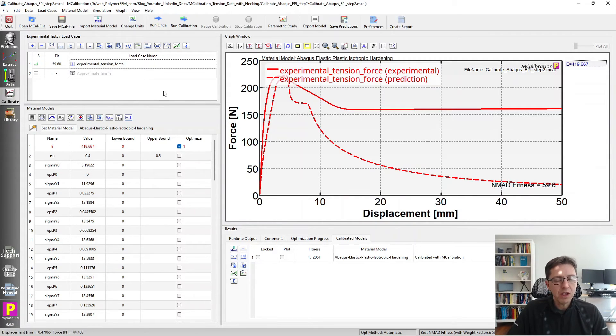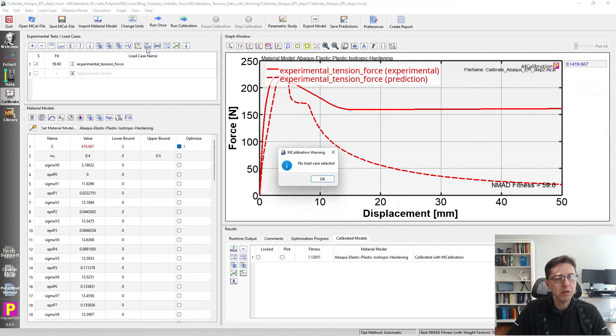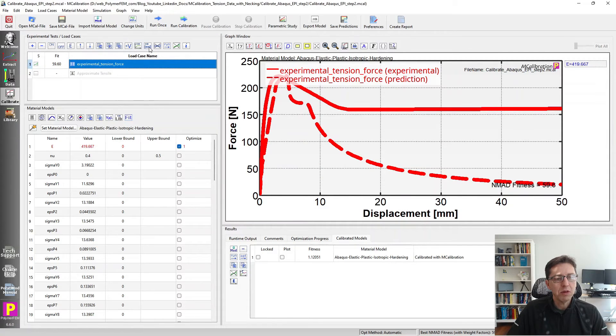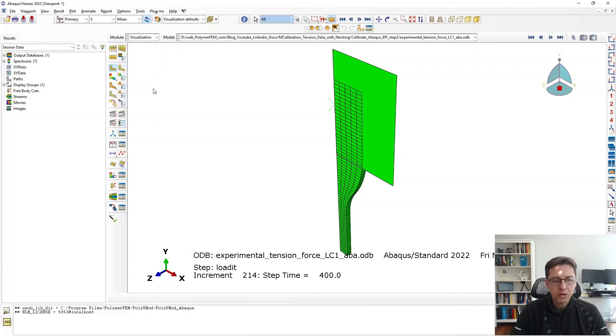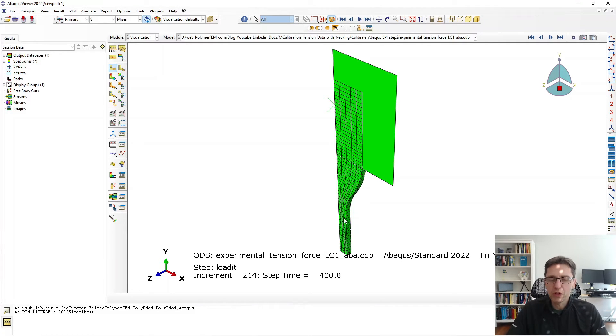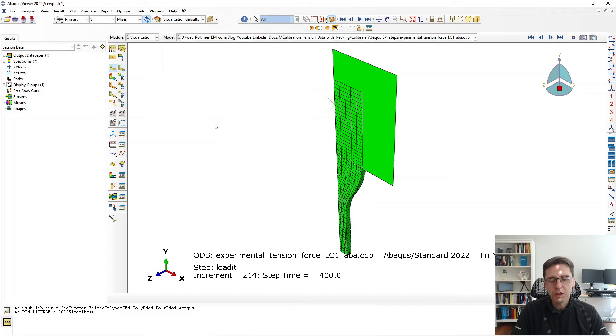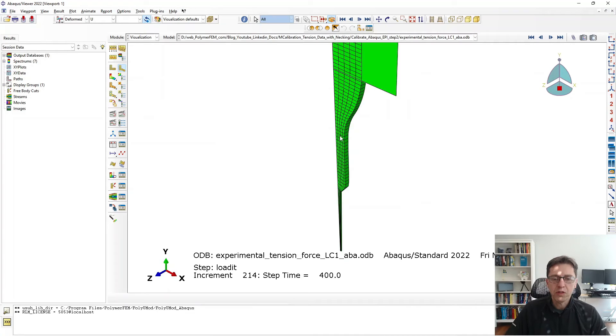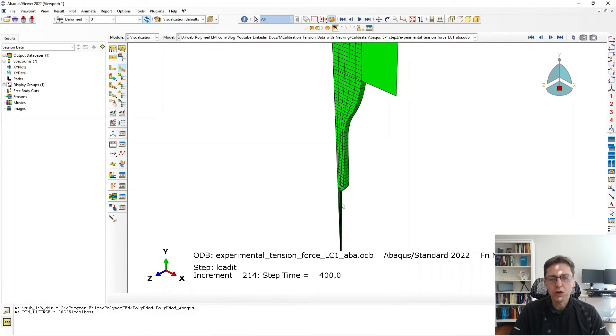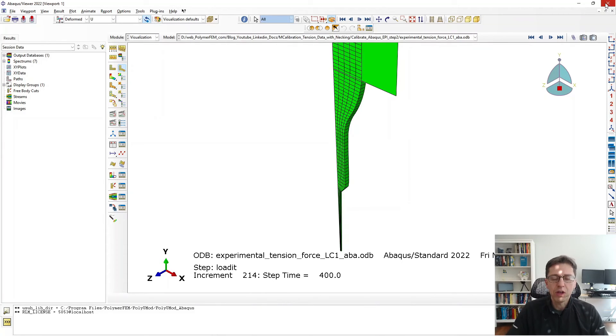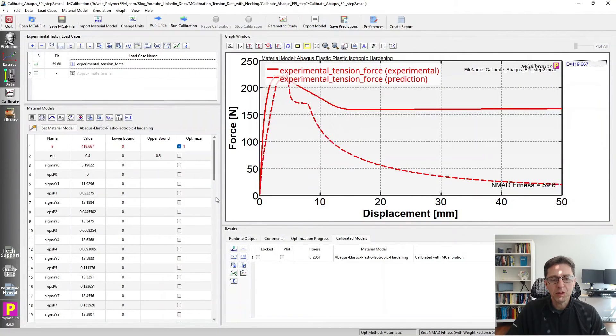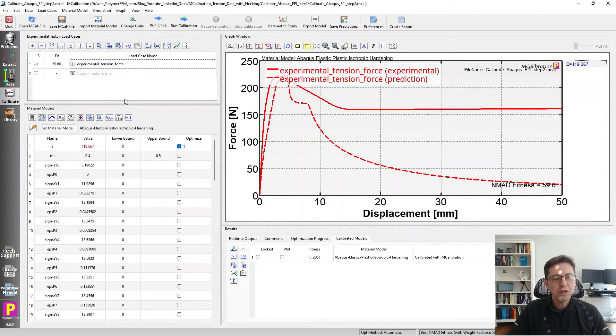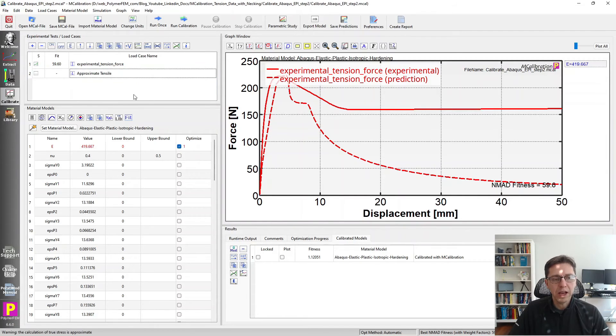Let's take a look using Abaqus CAE what the mesh looks like in this deformed state. I'm going to click on this button here after I select my load case, and that will open CAE for us. Here's Abaqus CAE. We see the deformed mesh and the symmetry that was used in this simulation. All of this was set up by MCalibration. If we look at the deformed mesh at the end of this calculation, we see a ridiculous localization of the deformation. The necking becomes absolutely insane here. An elastic plastic isotropic hardening prediction does not work very well in this case unless we recalibrate it, and that's tricky to do because the initial guess wasn't very good.